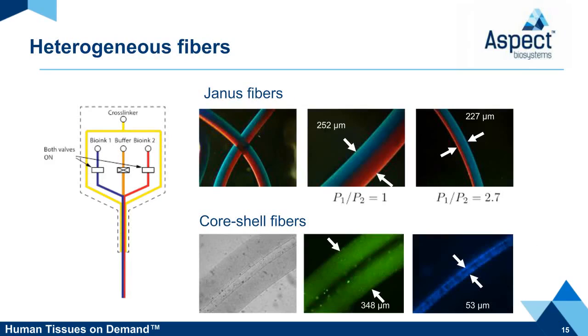At the fiber level, we can also introduce different compositional and structural features. At the top, you can see Janus fibers, where the fiber itself is composed of two different parallel material regions, one red and one blue dye. By controlling the pressure ratio between the material lines, we can vary the proportion of each material within the fiber. On the bottom of the slide, we demonstrate our ability to create core shell fibers, where the core can be a second material or can be empty to produce a hollow printed fiber.